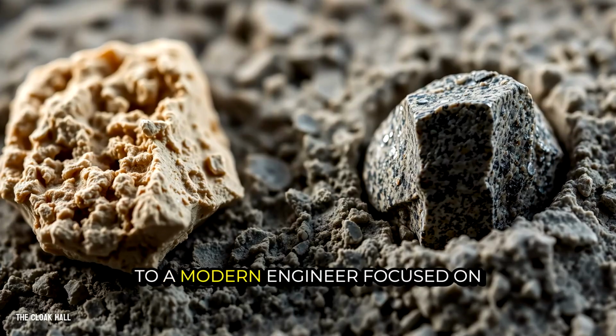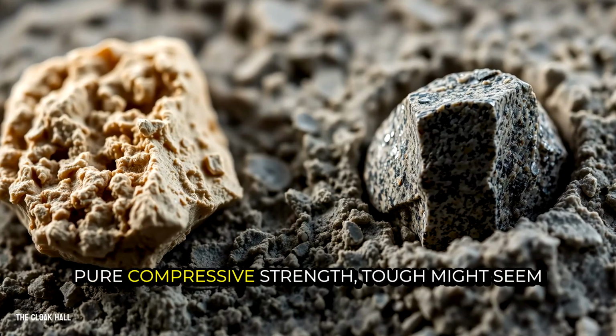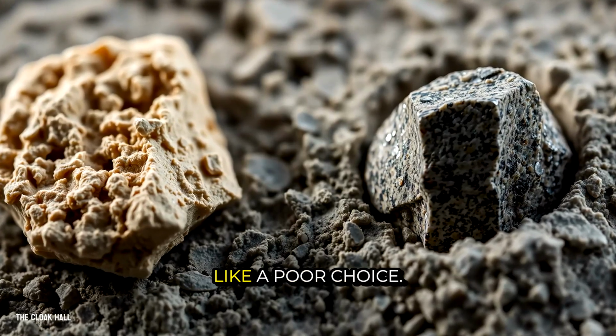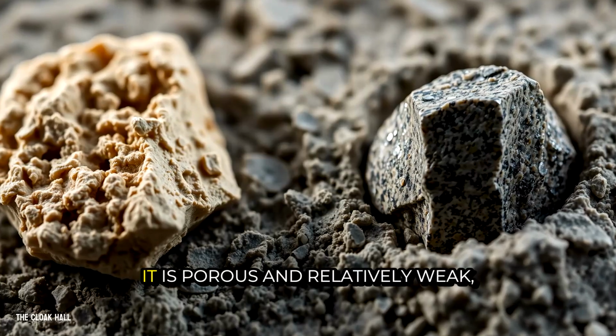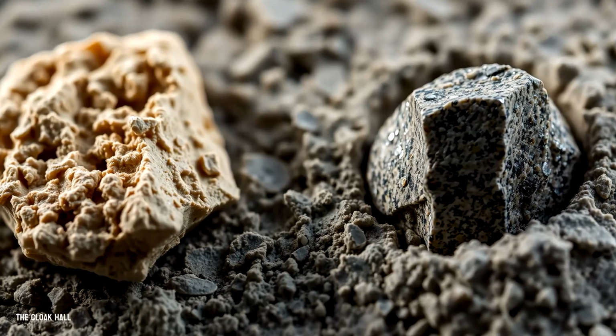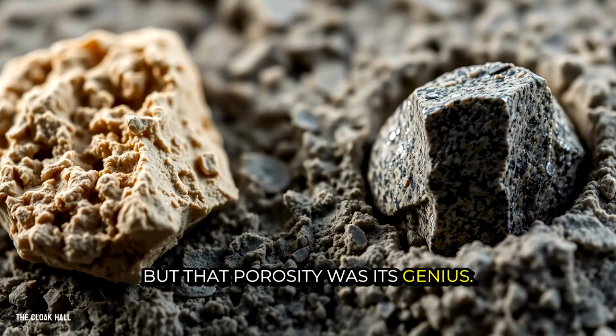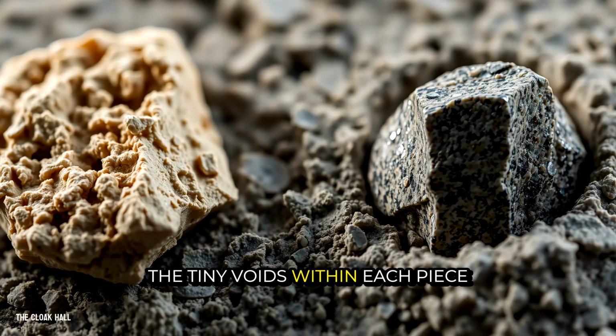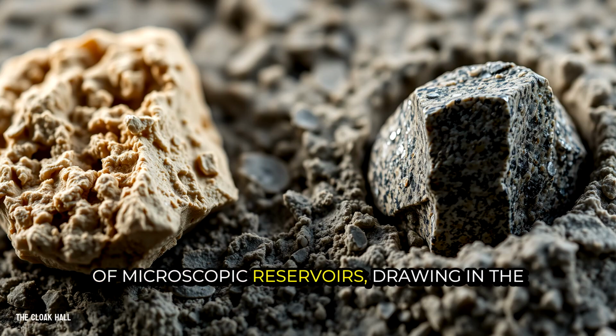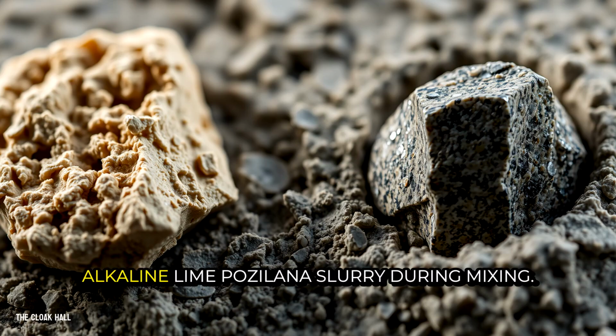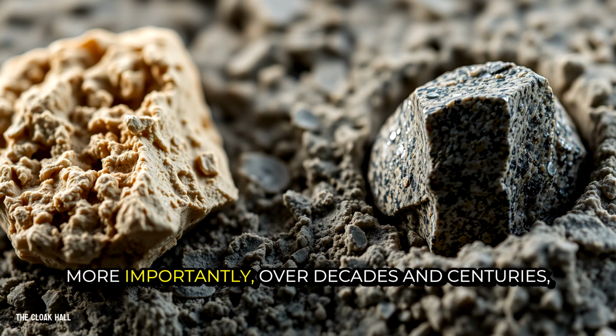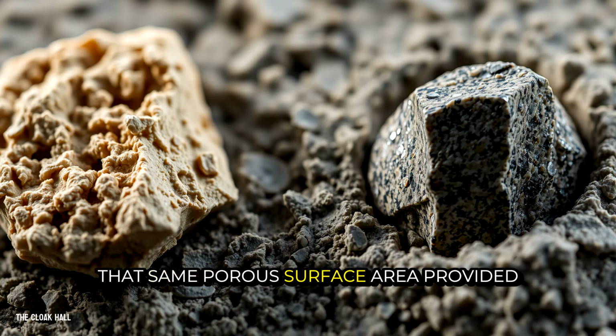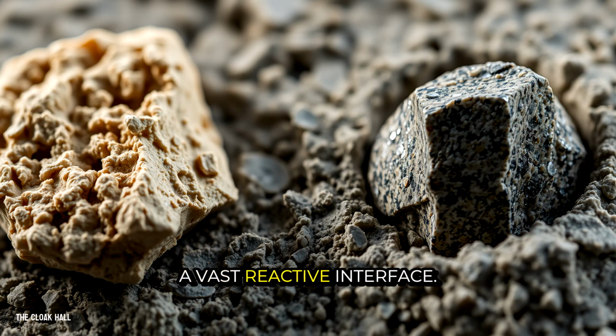To a modern engineer focused on pure compressive strength, tuff might seem like a poor choice. It is porous and relatively weak, but that porosity was its genius. The tiny voids within each piece of tuff acted like a network of microscopic reservoirs, drawing in the alkaline lime pozzolana slurry during mixing. More importantly, over decades and centuries, that same porous surface area provided a vast reactive interface.